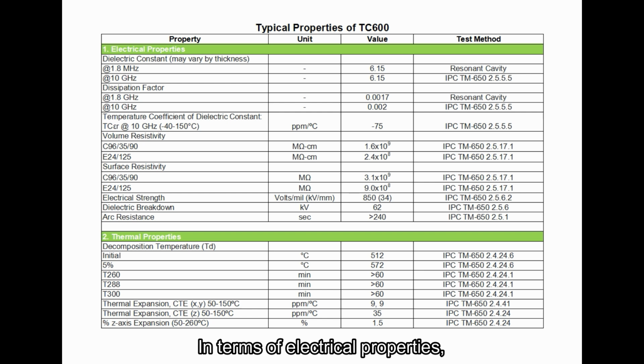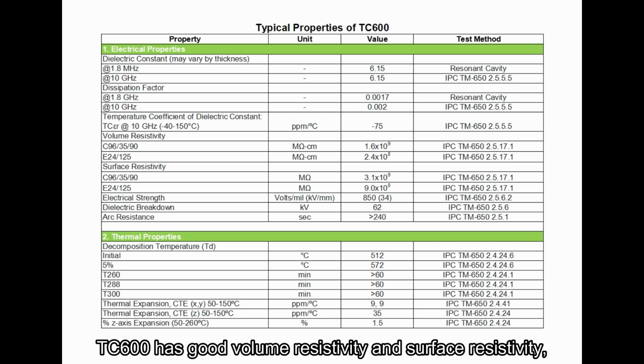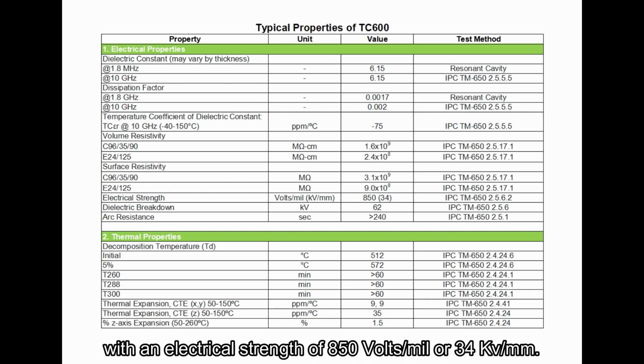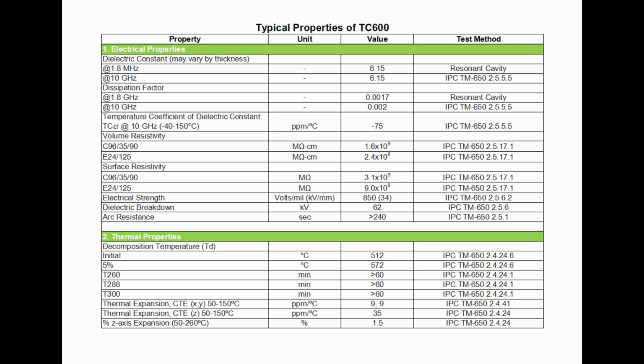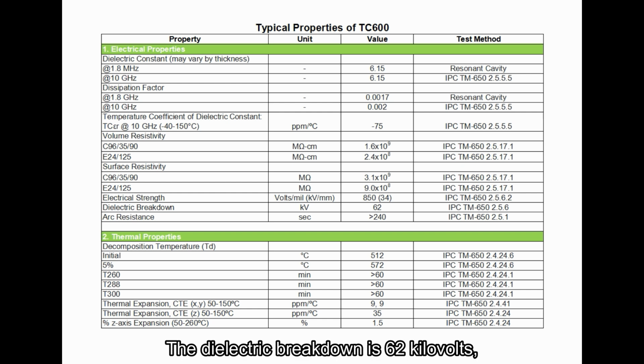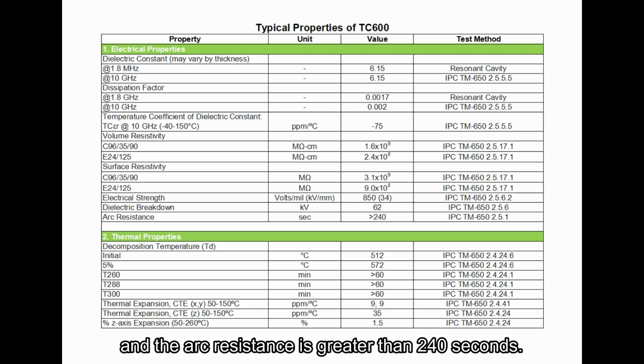In terms of electrical properties, TC600 has good volume resistivity and surface resistivity with an electrical strength of 850 volts per mil or 34 kilovolts per millimeter. The dielectric breakdown is 62 kilovolts, and the arc resistance is greater than 240 seconds.